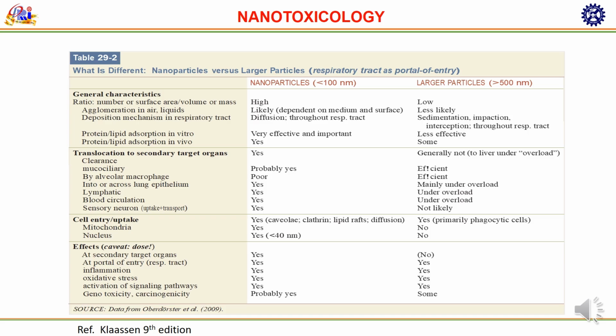Both nanoparticles and larger particles have local effects such as irritation and inflammation. Both induce inflammation, but nanoparticles do so at much lower doses. Oxidative stress: nanoparticles can generate reactive oxygen species (ROS) rapidly due to their high surface reactivity. Larger particles can also cause oxidative stress, but at higher concentrations.